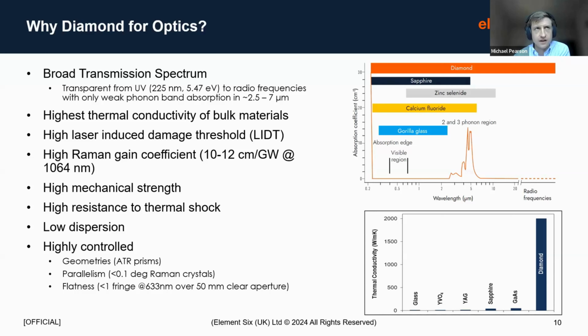The next thing that is very often important in optical applications is the high thermal conductivity of diamond. Certainly our optical grade diamond has a thermal conductivity that is in excess of 2000 watts per meter Kelvin. For those of you that aren't used to thinking in terms of thermal conductivity values, the graph on the bottom right gives a useful comparison between some other common materials used for optics against diamond. So typically optical materials will have thermal conductivities in the single digit or tens of watts per meter Kelvin. And as I said, optical grade diamond, we're in excess of 2000 watts per meter Kelvin.